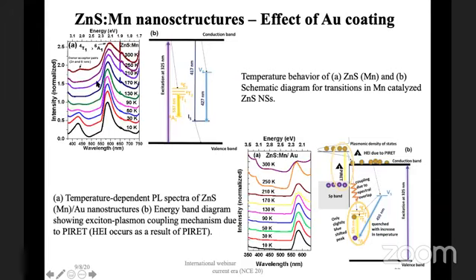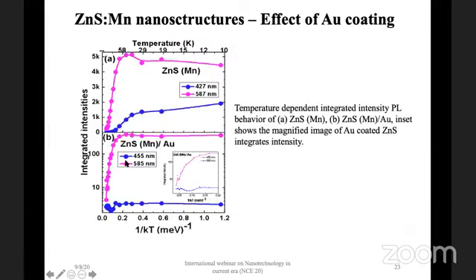They are given schematically over here. Now what happens is we put gold on top of it. What we see is complete elimination of this blue band and a strong emergence, even the intensity becomes much stronger, of this red, yellowish-red band. And we ascribe this process to the Förster process, which is happening over here. We are still trying to work out the theoretical aspect of this using simple laser equations, Einstein equations, to explain how this energy transfer happens between the plasmons and the excitons of the zinc sulfide. Now these excitons are the bound excitons. These are not free excitons. Free excitons are seen somewhere around 320, 325 nanometers, which we don't see.